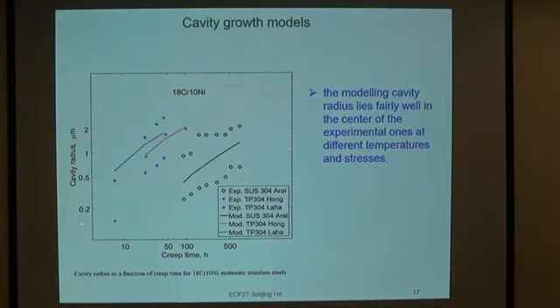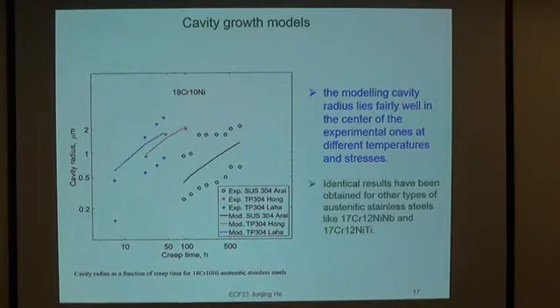And also here is the cavity radius as a function of creep time. It's for 18 chromium 10 nickel austenitic stainless steels. So it's very clear that the modeled cavity radius lies fairly well in the center of the experimental ones. And also identical results have been obtained for other types of austenitic stainless steels like 321 and 347.